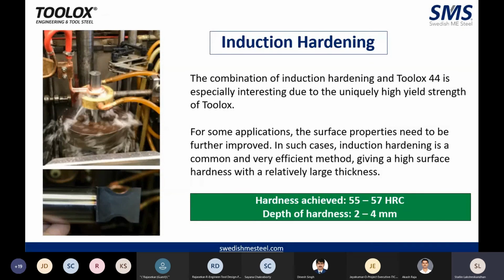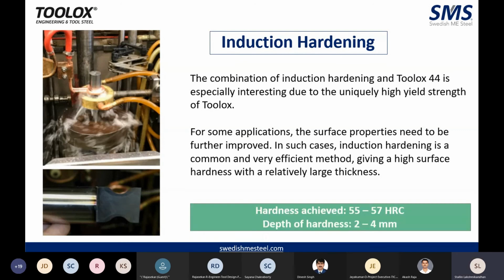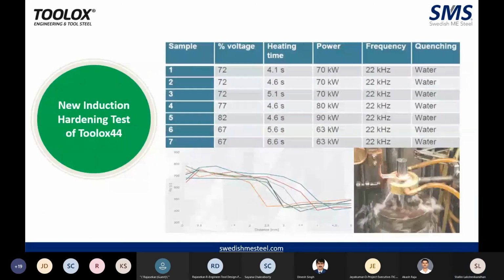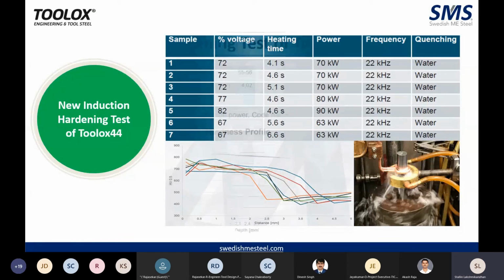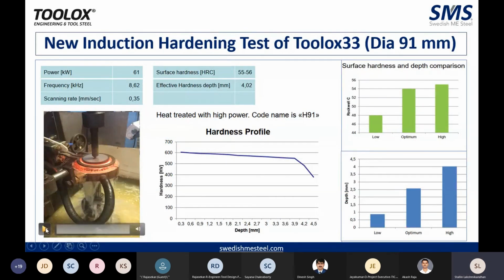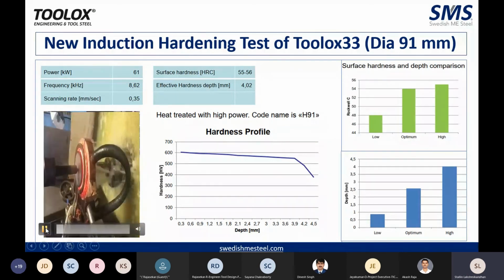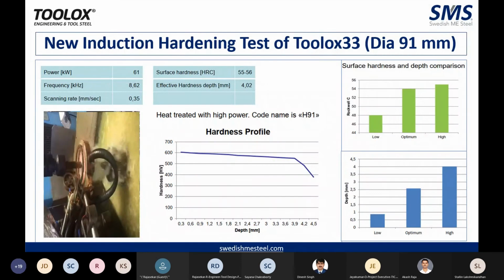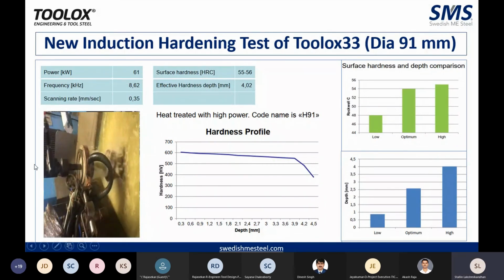Induction hardening with Toolox 44 is also a very interesting combination, particularly due to the high yield strength of Toolox. With induction hardening of Toolox 44, the hardness you can achieve is 55 to 57 HRC with a hardness depth of 2 to 4 mm. So these are the parameters which we have done. This is a short video of Toolox 33 die. As you can see, the effective hardness depth is 4.02 mm with a surface hardness of 55 to 56.